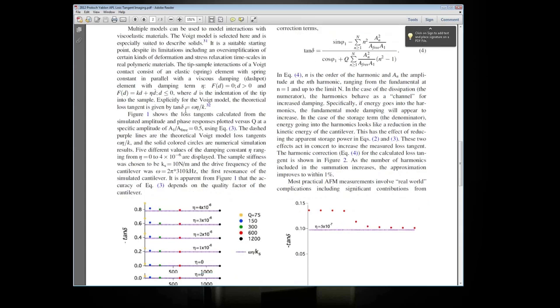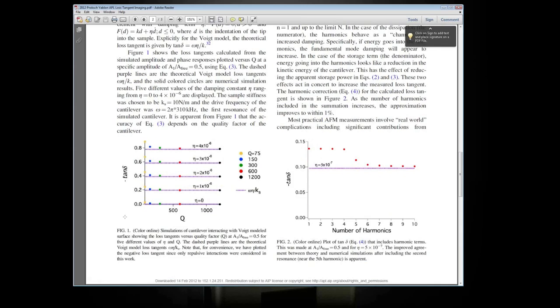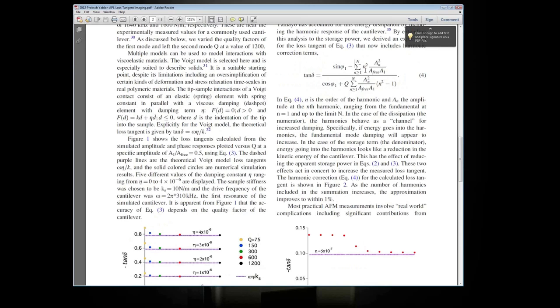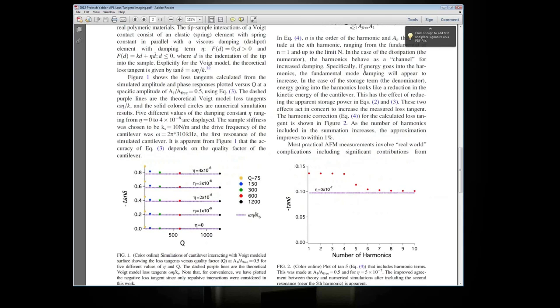If you look at this graph right here on figure 1, you see that the effect of higher harmonics is most important for quality factors that are small. So the errors associated with not accounting for those harmonics go up as the Q goes down. Finally, figure 2 shows the results of some calculations where we take this equation and use successive harmonics, and you can see as you go up through the second mode, the loss tangent approaches the theoretical value. I should say these particular results were all done with the VEDA simulation tool from nanohub.org. Arvind Raman's group at Purdue set this up.